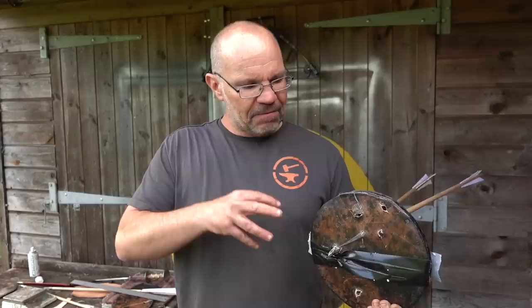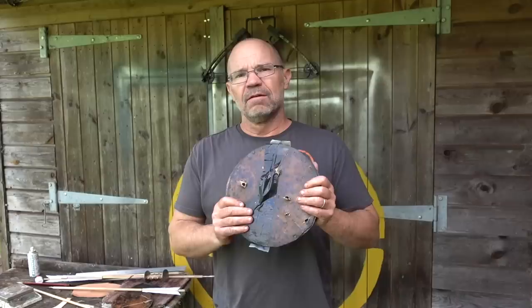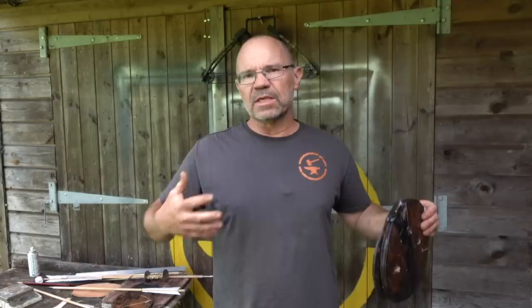And there we go — boiled leather. Can't tell you they made it like this, but I'm pretty sure they did. If they did make it like this, would it work? Yes it would. So I'm going to remove the arrowheads and weigh this sample. I've got a breastplate — I'll calculate the areas and tell you how heavy I think a breastplate would be were it made of this material on the front surface and thinner on the sides. 500 grams for that piece. I think you could probably do a three-ply breastplate with a five-ply reinforcement on the front for around about two and a half, possibly three kilos — roughly six to seven pounds. Boiled leather — right, good protection. See you next time for another lockdown longbow. Maybe gambesons, maybe mail, who knows?